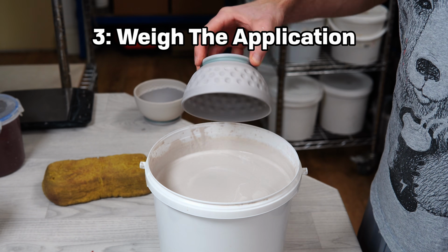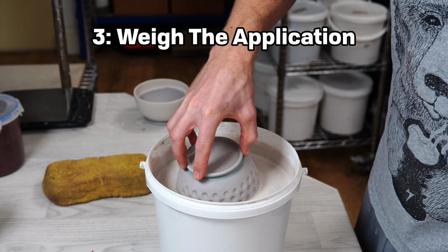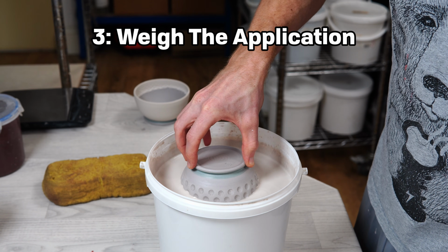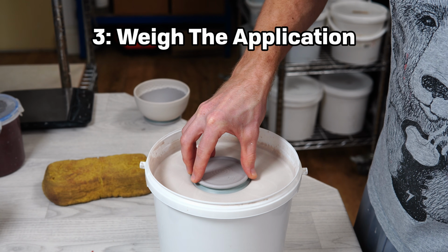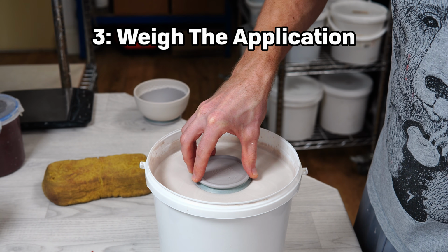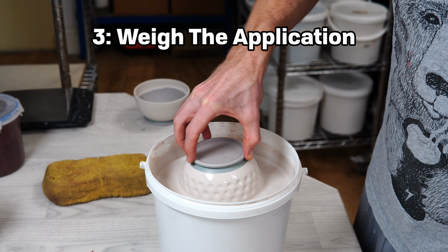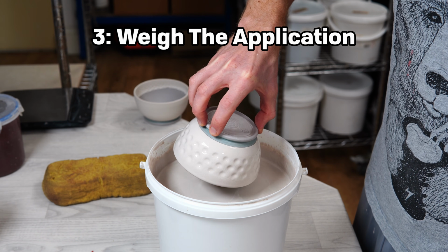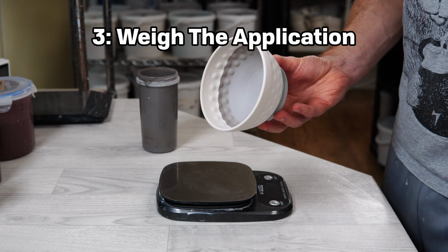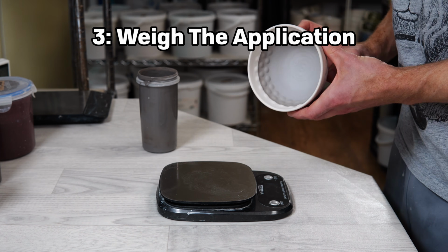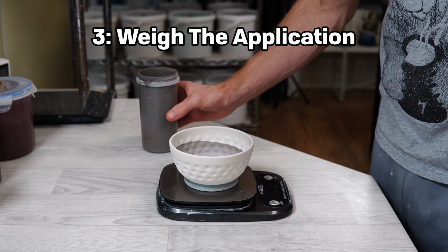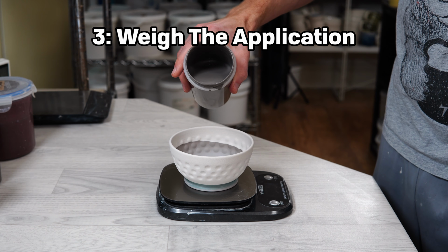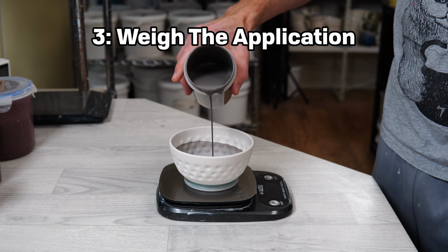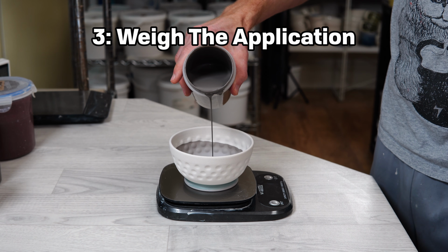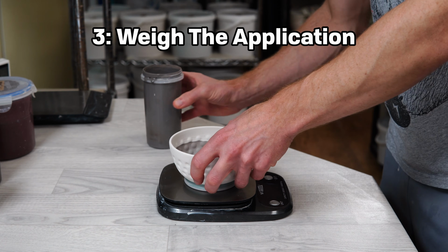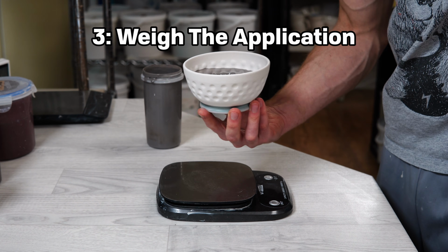Weigh the application. The easiest way to measure how much glaze is being added to a test or a full piece is to weigh it before and after the application. Dipping time on its own is a fairly meaningless number, especially when comparing your application results to someone else's. The porosity of a clay is determined by the clay body and the bisque temperature. Two different pieces could take up a totally different amount of glaze even if they were dipped in the same bucket of glaze for the same amount of time. If you're going to pay attention to one number when testing glazes, weight of application is the one to track.